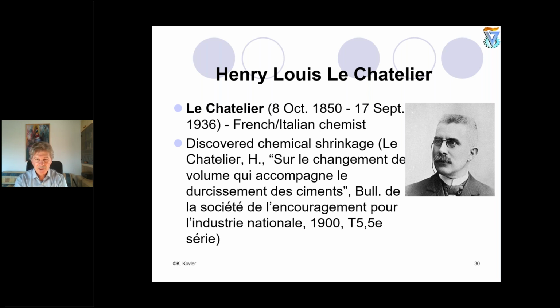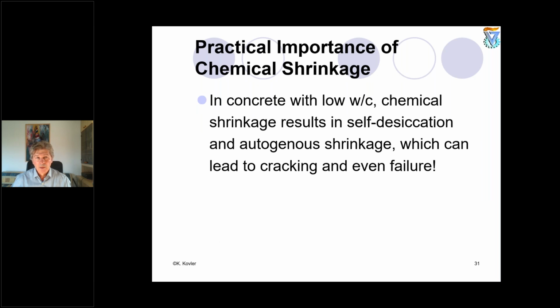He discovered chemical shrinkage more than 120 years ago. In 1900, he published a famous work explaining what chemical shrinkage is. What is the practical importance of chemical shrinkage? In concrete with a very low water-cement ratio, I'm speaking about high strength, high performance concrete, chemical shrinkage results in self-desiccation and autogenous shrinkage, which can lead to cracking and even failure.